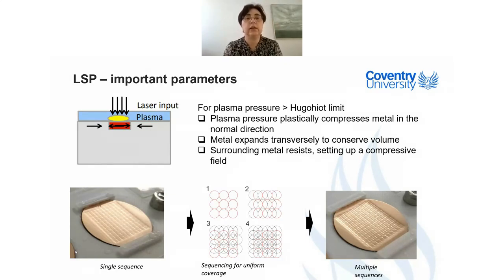So here is the video. As you see, we have the part. The green light is not a laser. It's just light showing you where the laser pulse is coming from. Infrared is used in this particular case. You have the black tape. There is a water layer. You see the water layer is really thick, a couple of millimeters. And laser pulses are coming next to each other, ablating the material. And at the moment when the plasma is no longer confined, you see the splashes back.